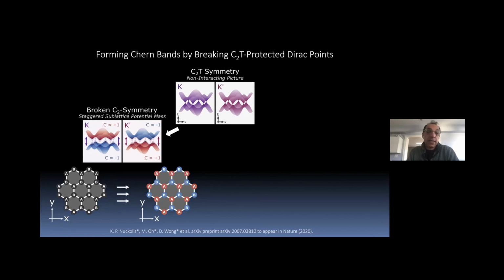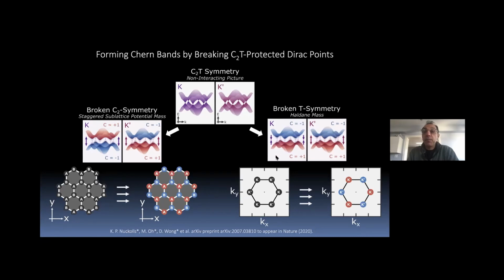Let me just say, I showed you the example from David Goldhaber-Gordon and Andrea Young, of how you get Chern insulating states by breaking the AB sublattice symmetry. This is in real space. You can think about what we are observing as in momentum space. You have the K, K prime symmetry in the system, and if you introduce time reversal symmetry breaking, just like Haldane did in his famous model, you form these Chern insulating phases that we are observing. That's the way it comes about in our experiments: you have to break the time reversal symmetry. So the system has some magnetism developing, and it's basically being aligned when you apply a little bit of magnetic field.